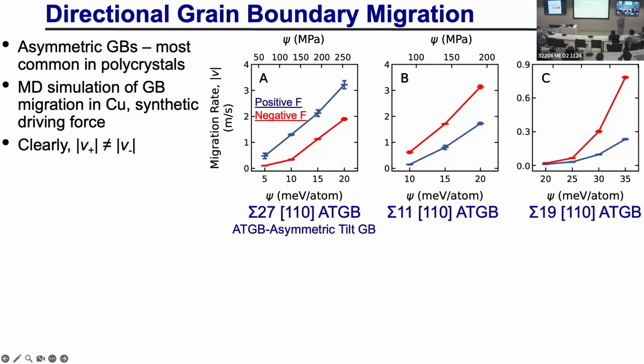Okay. And we've repeated this for something like 25 different types of grain boundaries in 3 or 4 different materials and with 3 different kinds of driving forces. And this is the generic conclusion that the velocity in the positive direction is not equal to minus the velocity in the other direction. And I just want to point out, by the way, for those who know this notation, this is just a label for what kind of grain boundary it is. When I write down ATGB, it stands for asymmetric tilt grain boundary, which is to say there's no mirror symmetry across the boundary plane. It's asymmetric. Okay. So those are 3 different boundaries.